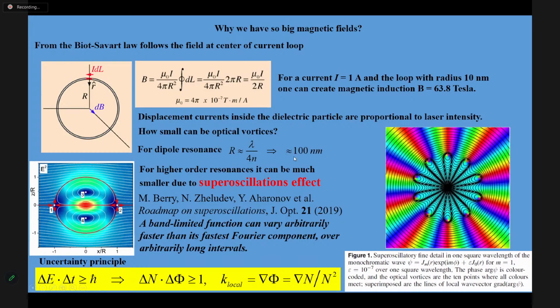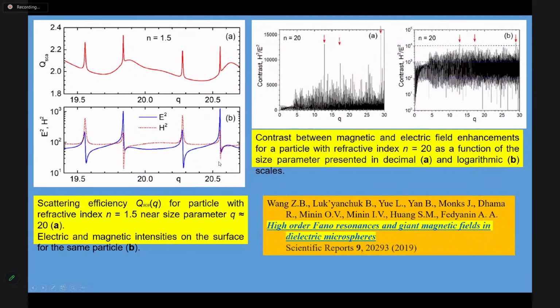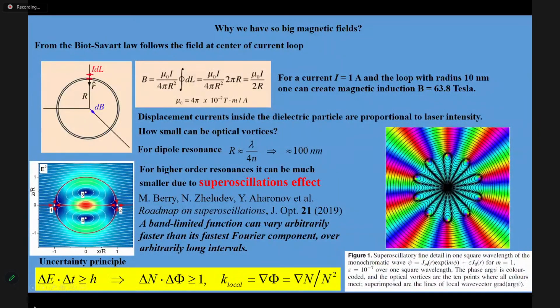If you see the dipole resonance, it typically produces vortices of 100 nanometers, which is insufficiently small. However, we have the super oscillation effect. When we have an optical singularity, then around this optical singularity we have a variation of phase, which is 2 pi around this point, and it creates a huge localization near the central point where the Poynting vector is equal to 0.